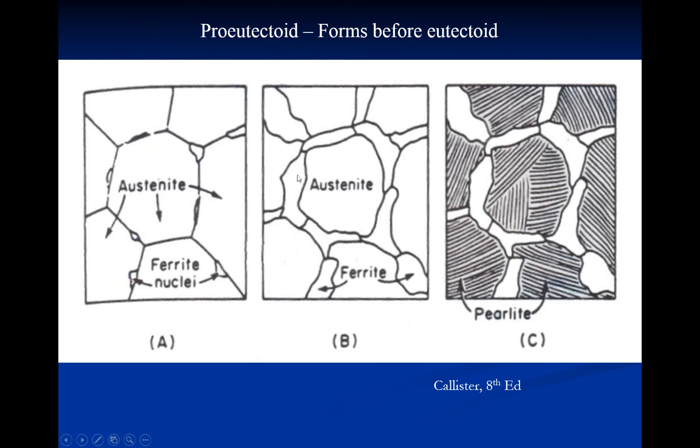So your prior phase diagram information, tie lines, and reverse lever law should allow you to identify that we have about 1/3 ferrite at this point. The ferrite is poor in carbon from the tie line. The austenite, which is 2/3 of this surface, is going to be richer in carbon than the overall material. And this is running about 0.77% carbon at point C on the phase diagram.